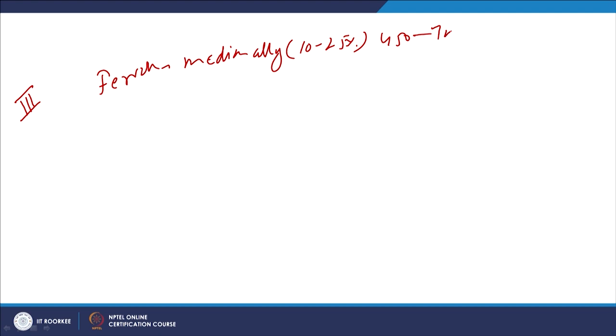Then there is a third category. These are again ferrous based medium alloyed steels, medium alloyed materials, and these have 10 to 25% of alloying elements, and the hardness is in the range of 450 to 700 HV. So the hardness is on the higher side, and these are used for high temperature applications, meaning abrasion under high temperature conditions like 300 to 600 degree centigrade.